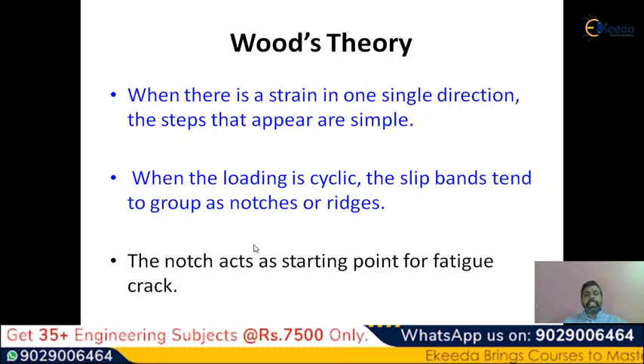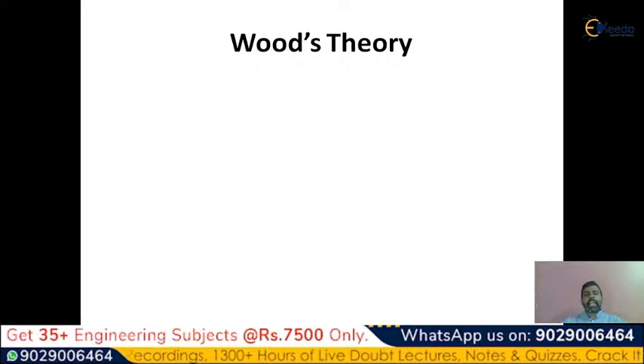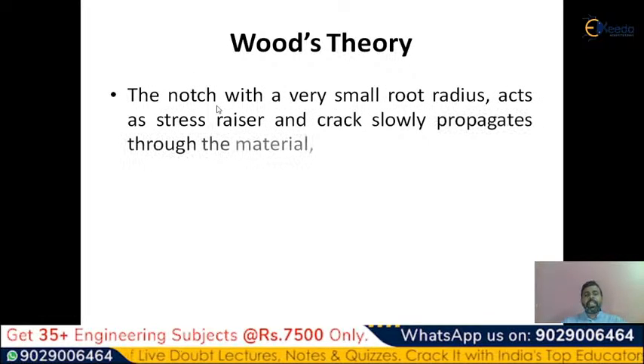The notches are generated due to the forward direction of the slip band and the backward direction of the slip band, or the forward strain and the backward strain. The notch acts as a starting point for the fatigue cracks. So these notches are very dangerous. If you are unable to avoid or reduce these notches, automatically the entire material is going to get cracks. The notch that is going to generate here starts with a very small root radius. You cannot identify it with the naked eye. That's the biggest problem. That's what Wood's theory says.